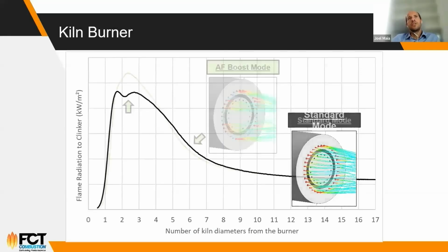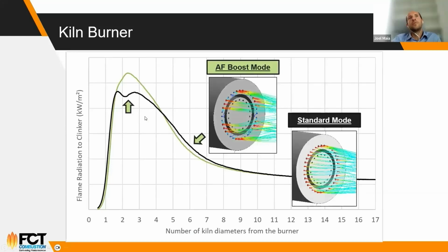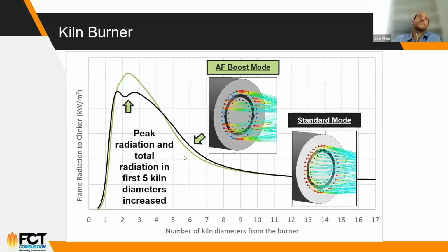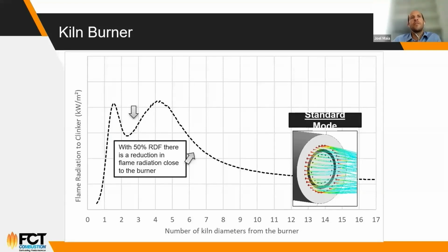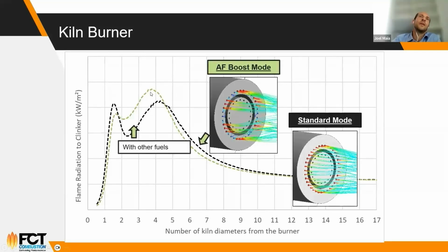Again, the same curve, just to illustrate again. Boost mode, we would go much higher in the peak radiation, and also the flame would get shorter. And this is also the same for different types of fuel. So here with 50% RDF, for example, obviously we have different peaks. So for coal, one for the RDF, but when you go to boost mode, these 2 peaks, first of all, they go up. So you are burning the RDF much better. The RDF goes back closer to the burner, and the 2 peaks, they come closer together. So you don't have this colder flame in between them.